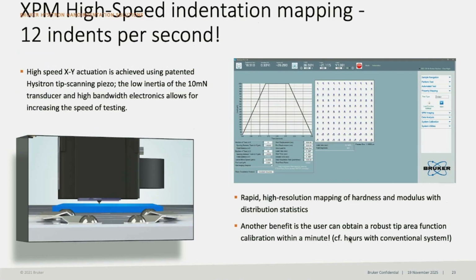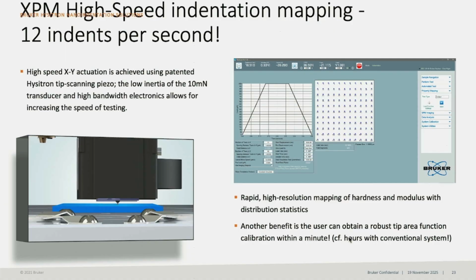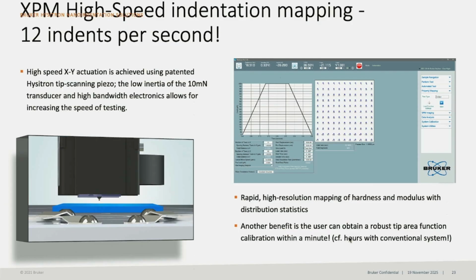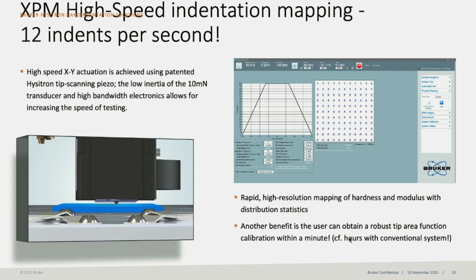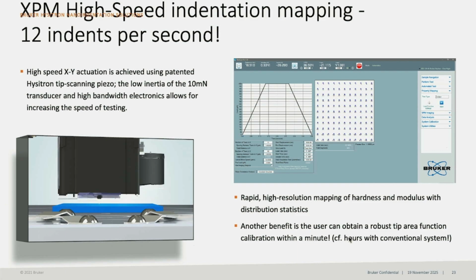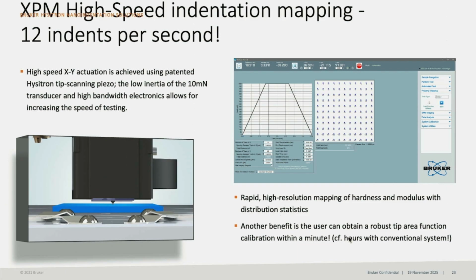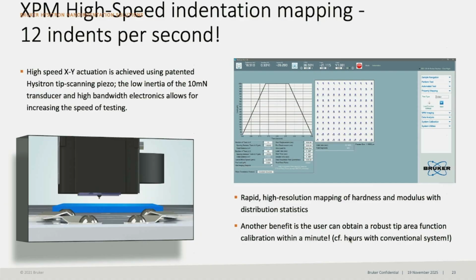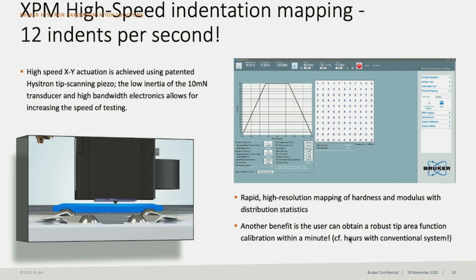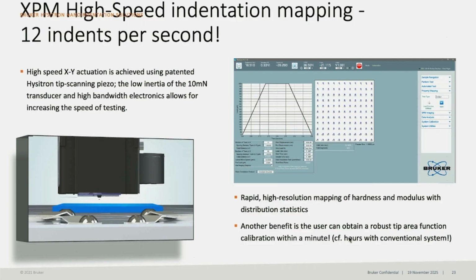And nowadays, we are also using the nano indenter as a high-speed indentation mapping. So previously, we were talking about the nano indenter doing one indent, right? Every indent takes 5 minutes. It's a very slow technique. But in the recent 10 years, it's getting popular to have the properties mapping. So we are using the high-speed indentation on the surface. It can allow you to test 12 indents per second. So this is a kind of fast technology for the nanomechanical properties mapping.